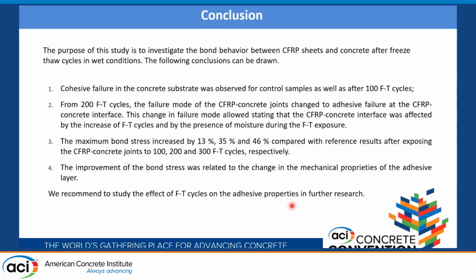The maximum bond stress increased by 13, 35 and 46% compared with the reference results after exposing the CFRP concrete joints to 100, 200, 300 freeze-thaw cycles respectively. The improvement of the bond stress was related to the change in the mechanical properties of the adhesive layer. And we recommend to study the effect of freeze-thaw cycles on the adhesive properties in further research.